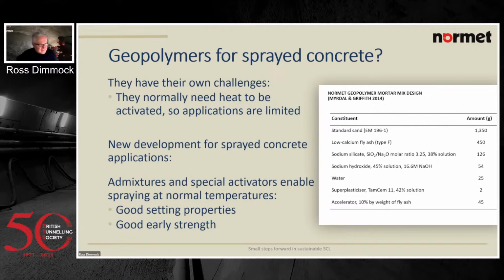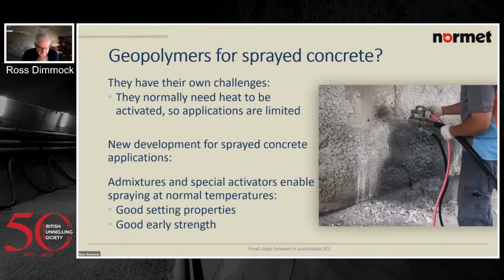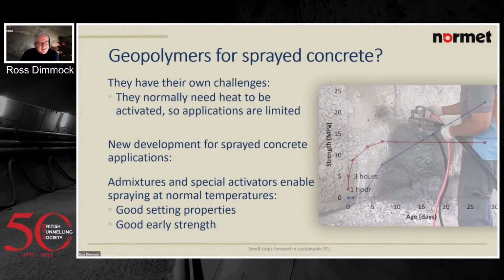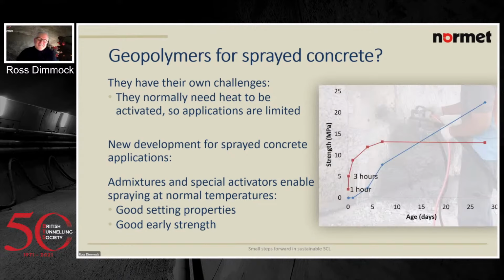I know Charles Allen is itching to help me look at this, and because I have an issue, we've made this really work to some extent. This is cement-free spray concrete. We sprayed it, and we get superb early strengths with it. We can get 5 MPa in 3 hours, which is great.